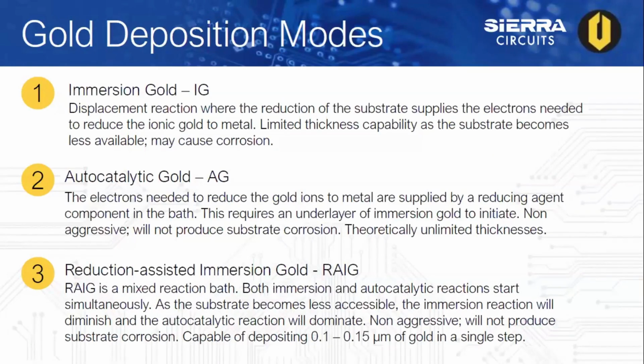Now here we have gold deposition modes. One, we start with immersion gold. It's a displacement reaction where the reduction of the substrate supplies the electrons needed to reduce the ionic gold to metal. It has limited thickness capability as the substrate becomes less available and may cause some corrosion.